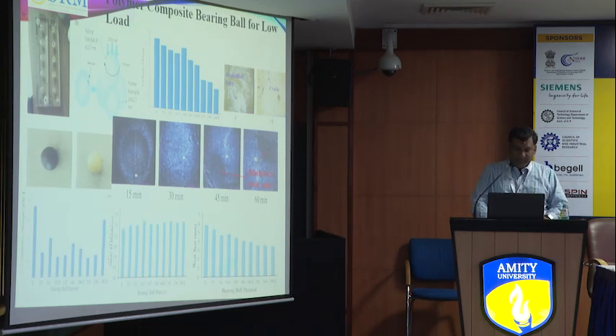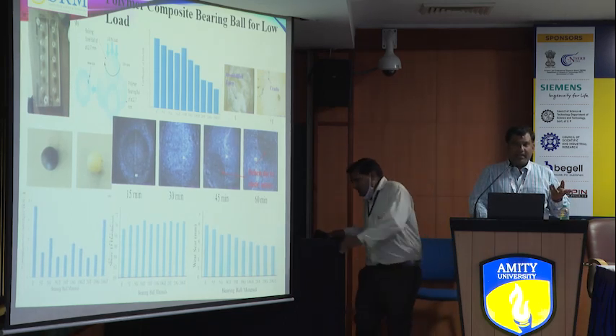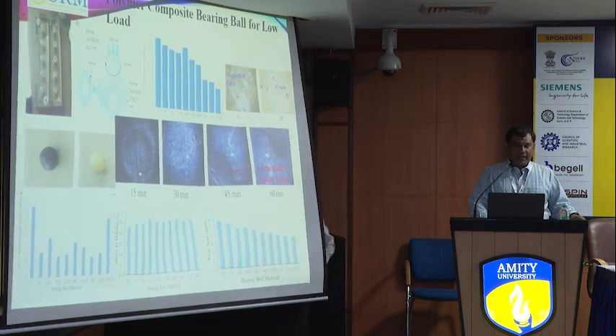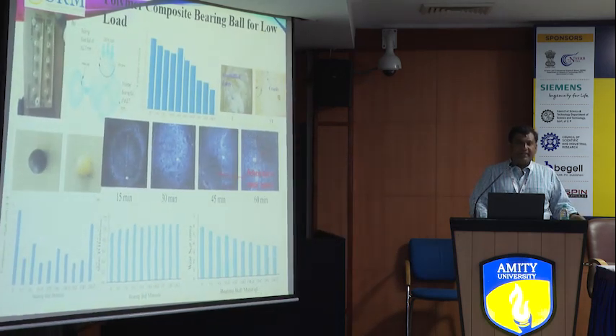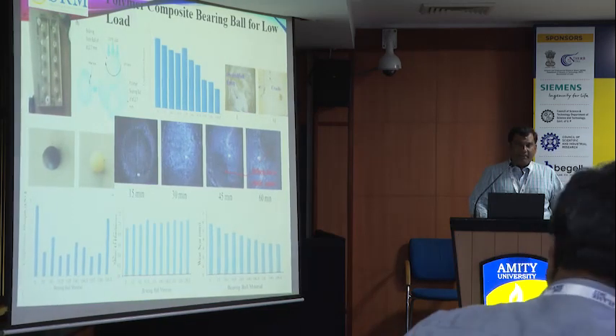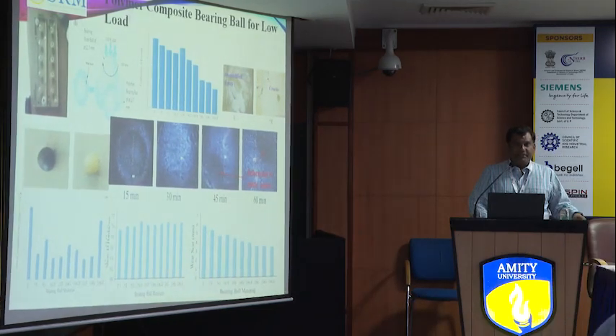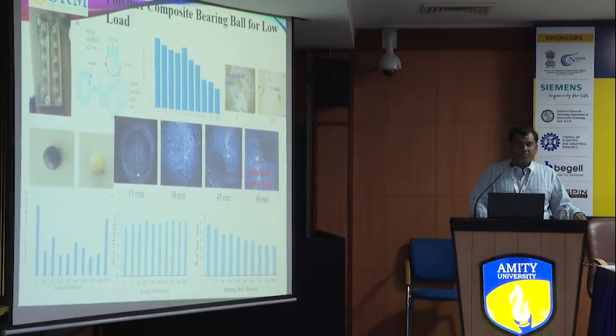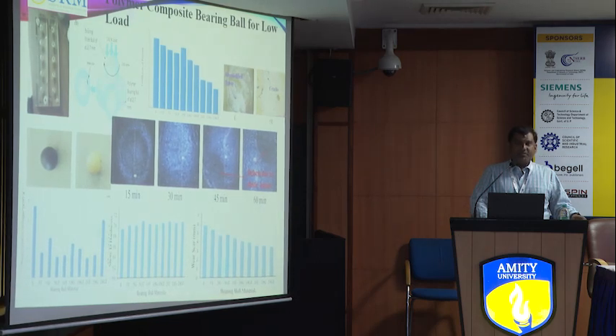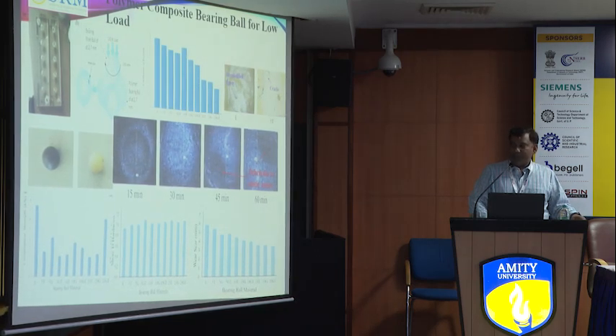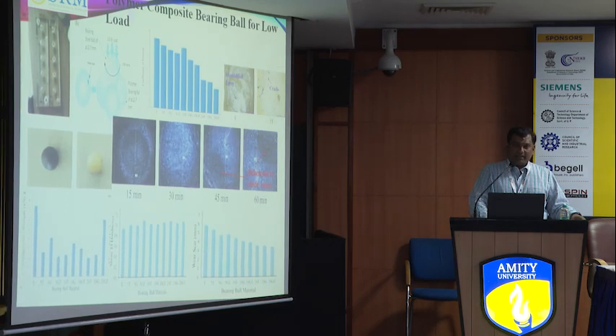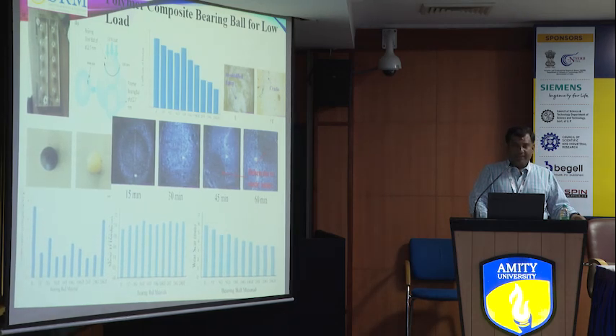Further, we have tested the compressive strength of the polymer. You know that we only conducted the Shore hardness test. We are not conducting Rockwell, Brinell or Vickers hardness tests, as those are only for metals. For polymers, the Shore hardness test is used as per the ASTM standard, and we observed that the graphite talc ball is good in terms of compressive strength and also in terms of wear scar.